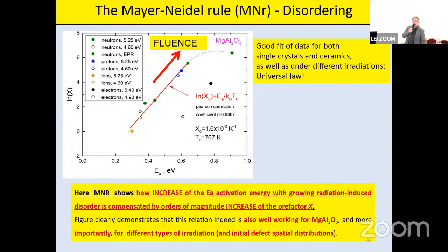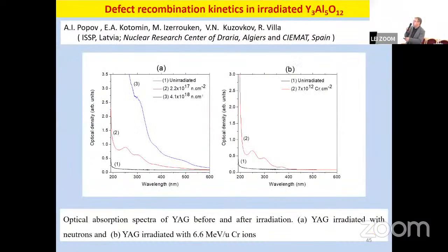We used mostly xenon, krypton and uranium ions for our measurements, but for the moment it's quite difficult to answer the dependence of such annealing as a function of swift heavy ion energy and type of the ions. So for the moment everything works well for each energy and for each type of ions. Maybe later we will improve this model, but this may not be very important because for the moment everything works well and we could evaluate what we need.